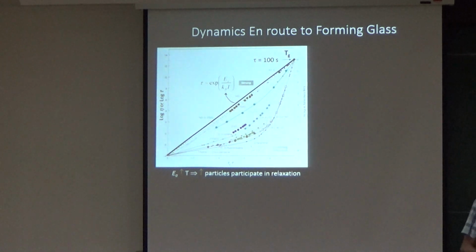So one thing that you could look at is density correlations. So how does it decay? What happens is in this regime, when you're very far away from the glass, you get a simple exponential decay. But as you start approaching the glassy state, you see a plateau, and the plateau immediately doesn't die down, and that is some sort of a measure for what a glass would mean. Okay.